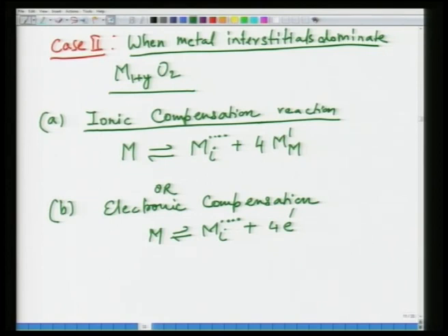These electrons which are created in these two cases are called quasi-free electrons, or if there is reduction, then it is often referred to as M'. In these solids, since you have quasi-free electrons present, these electrons can be a source of conduction as well, and as a result of the presence of these quasi-free electrons, many of these materials tend to be n type conductors.